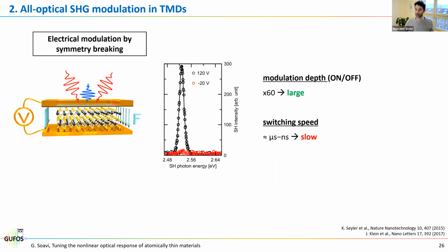So now by switching on and off the external gate voltage, they can switch on and off the second harmonic generation. Now, the advantage of this approach is that the modulation depth, so the on-off ratio, is very large. They observe up to a factor of 60. The disadvantage is that you are at the end limited in speed by electronics, and compared to optics, electronics is slow because the fastest speed you can switch on and off an electronic device is typically, let's say, gigahertz bandwidth. That means in the range of nanosecond response time.